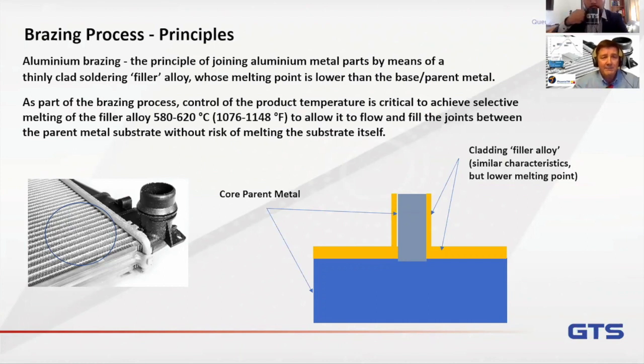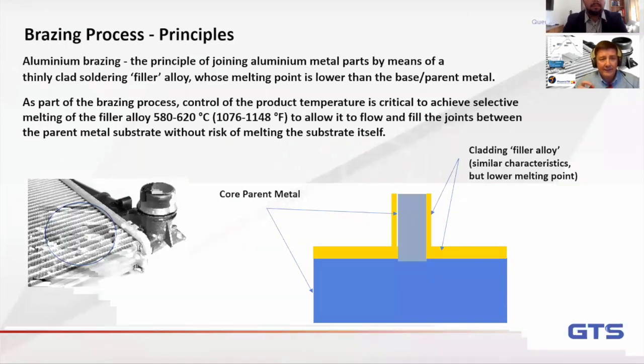So we need to be fairly accurate as to how we control the temperature of that radiator to prevent potential damage to the substrate in the actual brazing process itself. But we also need to control the temperature of the filler alloy so that it melts at the right rate, and then it flows, and with capillary action it fills the joint where you want the physical connection to be made, which is then reliable and will give the physical strength to the product post the brazing process itself.